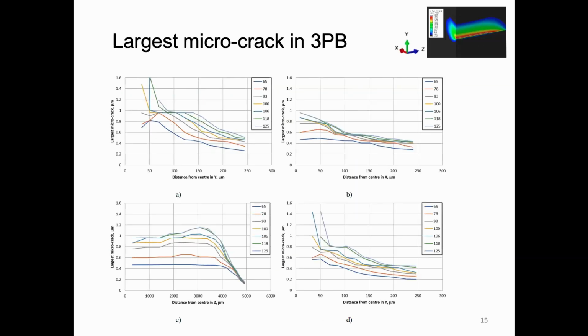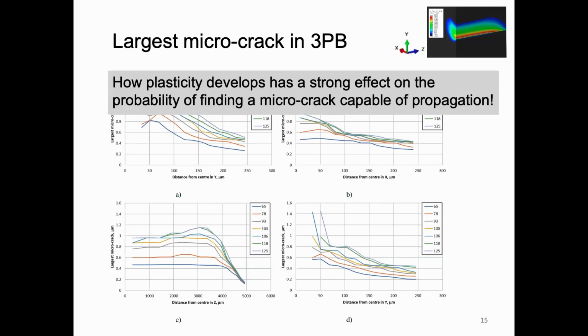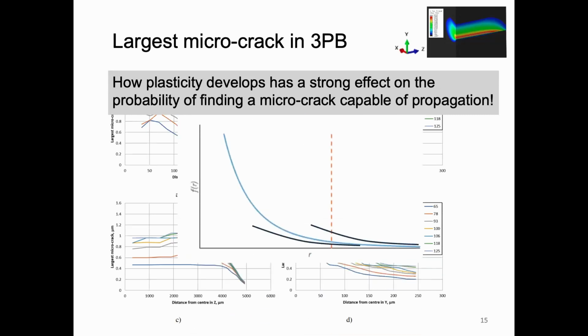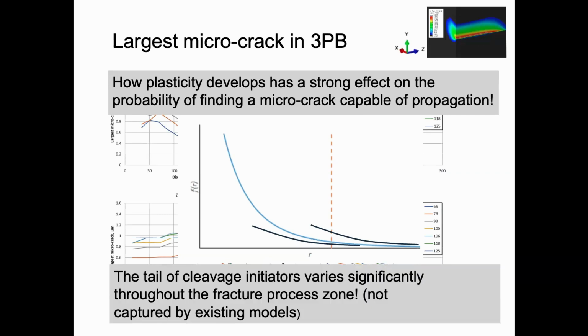And the second thing is the largest microcracks. The largest microcrack is also varying ahead of the crack, normal to the crack plane and along the crack line. And it varies quite differently in the low constraint geometry. So the takeaway from here is that the way plasticity develops has a very strong effect on the probability of finding a microcrack capable of propagation. If you assume a single curve, at some point the curve may be like that, and at another point like that. It can be changing everywhere. When you do one single calibration, you may be calibrating this curve, but in a different constraint or temperature condition, you need a different calibration. And so the existing models are not transferable. And the last point here is that the tail may vary significantly.